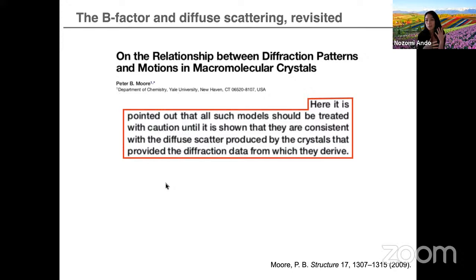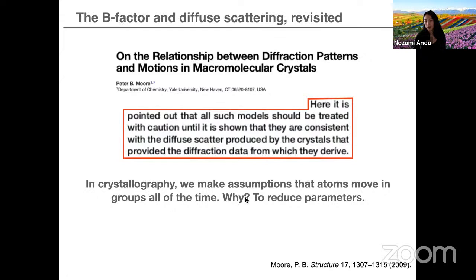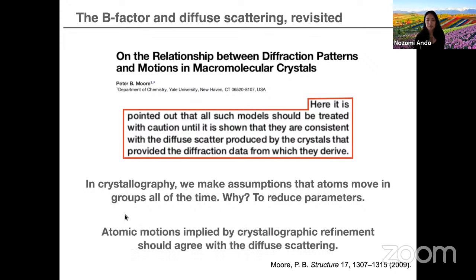And oftentimes we ascribe biochemical meaning to those motions. But his point was that the B factors alone can't tell you if those motions are realistic or not, and that they should be validated with diffuse scattering. So I said that we often make this assumption that atoms move in groups all the time. And there's a good reason for doing that, which is that an atom that's part of an amino acid should move with the rest of the amino acid. But the other practical reason is that it can reduce the number of parameters in the refinement. However, the key takeaway is that any atomic motions implied by refinement of a structure should agree with the diffuse scattering. And this is something that had not been done.